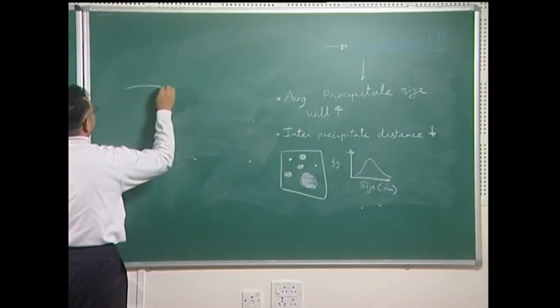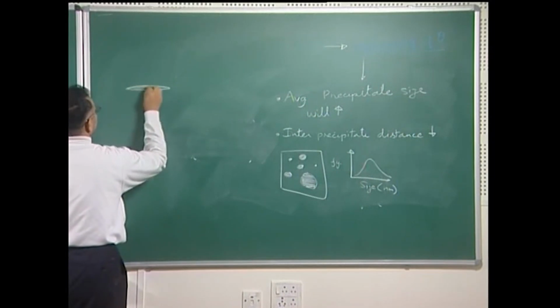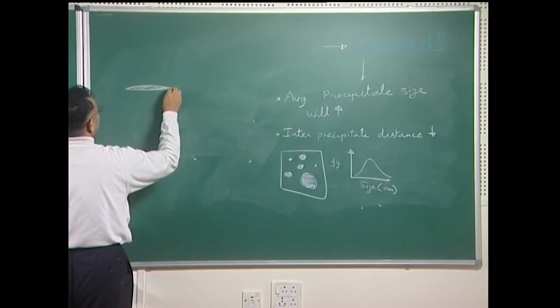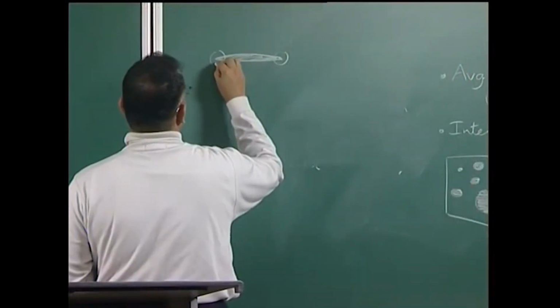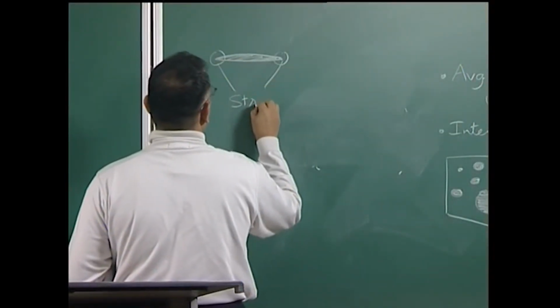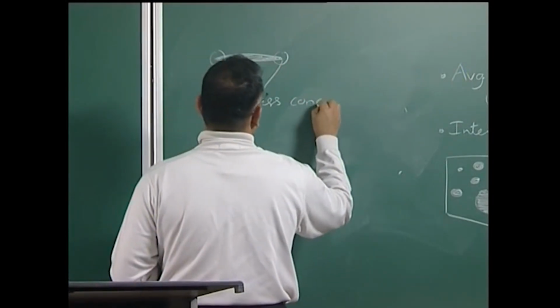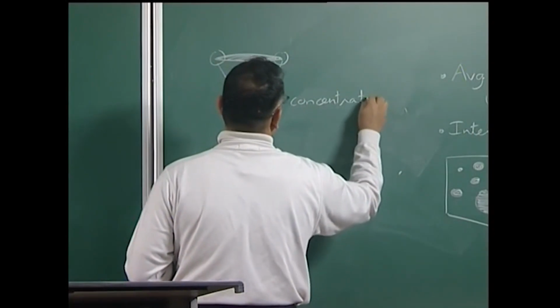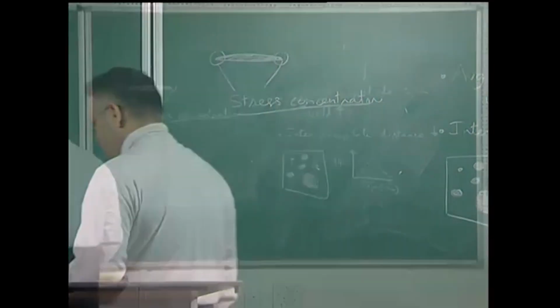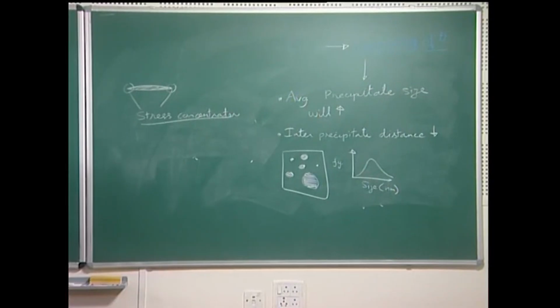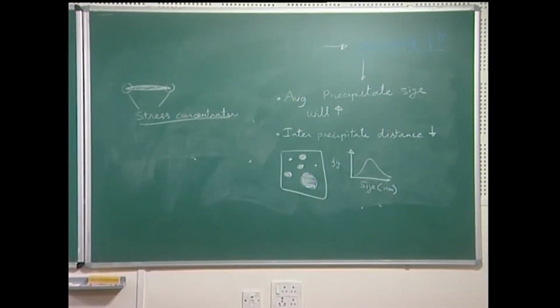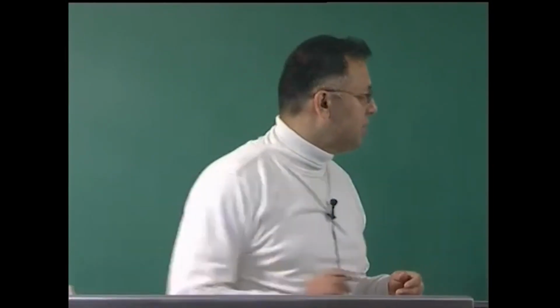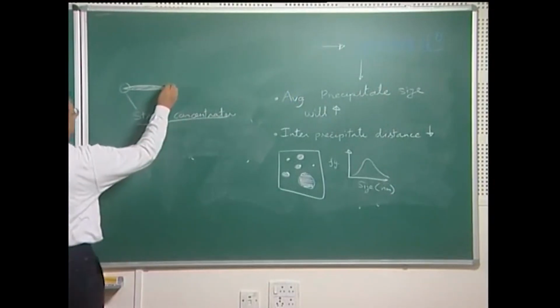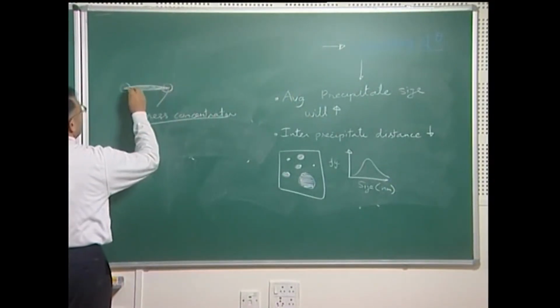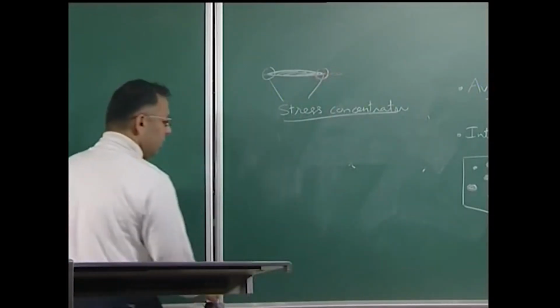So, I have a precipitate which is like this, and ahead of the precipitate this region acts like a stress concentrator. If this acts like a stress concentrator, then cracks may initiate at these regions which have been marked in this case by this circle. So, cracks could nucleate here and therefore propagate and lead to the failure of the material.